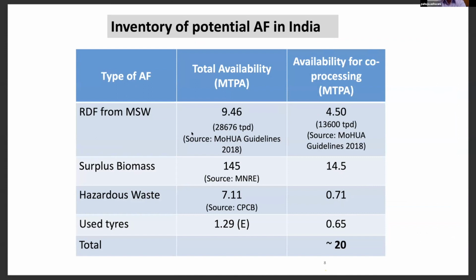Now, when we talk of the potential of alternate fuels in India, out of this MSW, 9.46 million tons of RDF can be made available currently as per 2018 data, and nearly 4.5 million tons can become available to the cement sector. Apart from that, there is surplus biomass available in huge quantities of around 145 million tons per annum, which is largely being either used by the renewable power sector or disposed of at the site itself. Again, hazardous waste, close to 7.11 million tons, is available, out of which nearly 0.71 million tons is available to the cement sector for co-processing.